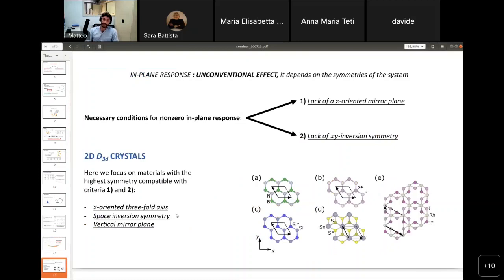Now, conversely to the out-of-plane response, that is actually an effect that we can call universal, in the sense that it is in principle allowed for any material, regardless of the symmetry describing the material, particularly in an inside-flat configuration, the in-plane response is an unconventional effect, in the sense that it depends on the symmetry of the system, or actually on the lack of symmetries of the system. Indeed, two conditions are necessary in order to see a non-zero in-plane response. The first one is the lack of a z-oriented mirror plane. The second one is the lack of XY inversion symmetry.